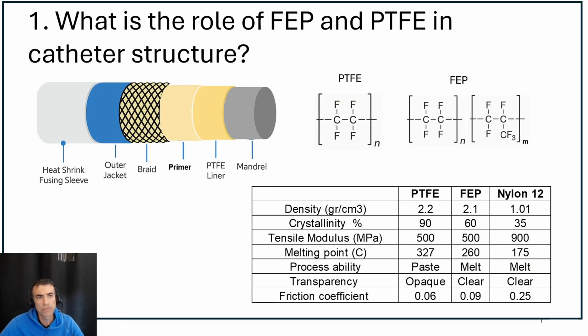Catheters are usually made of different polymer layers, and each polymer has a specific job in a catheter structure. In a typical catheter, PTFE is used as a liner, the inner layer of the catheter, because PTFE is very lubricious. It has one of the lowest friction coefficients among the polymers, and that makes it very easy for the guide wire to glide into the liner and makes it easy for the surgeon to operate when using the catheter.